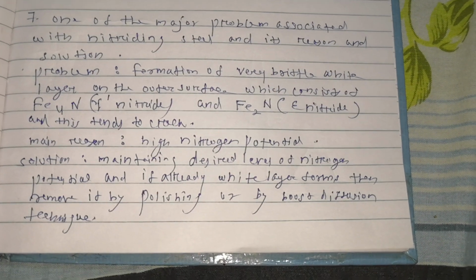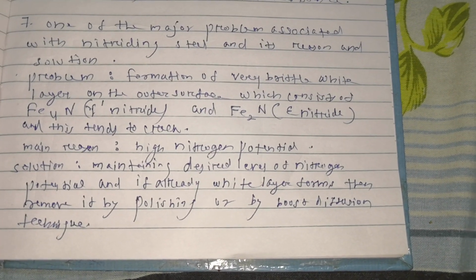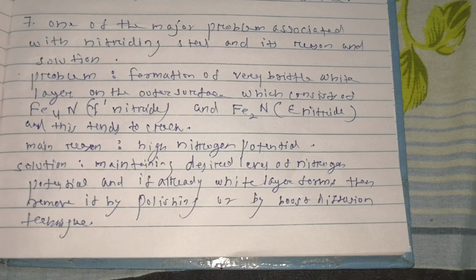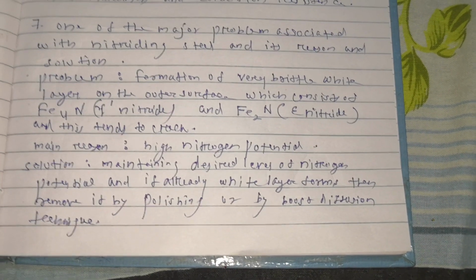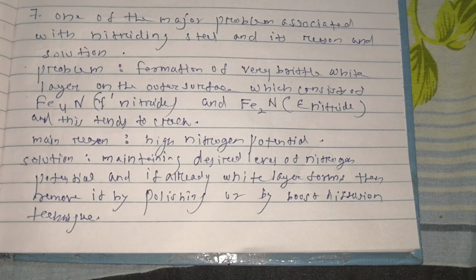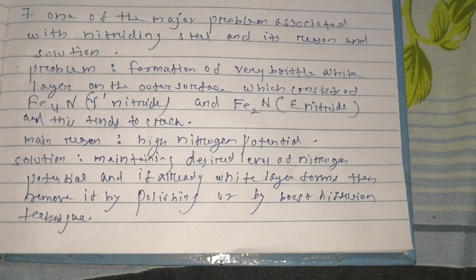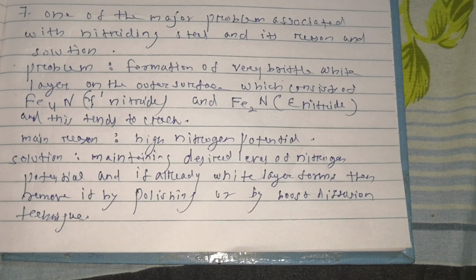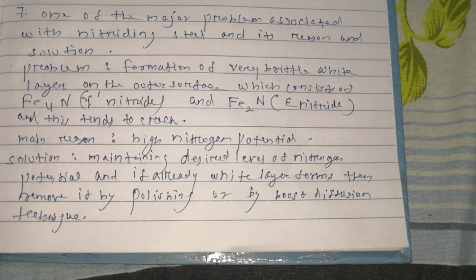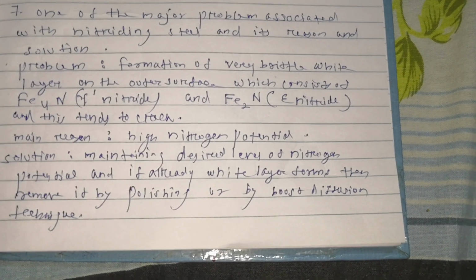And the main reason behind this phenomenon is high nitrogen potential. So the solution obviously will be to control the nitrogen potential at the surface of the steel. But if a white layer is forming, it should be removed by polishing or by boost diffusion technique.